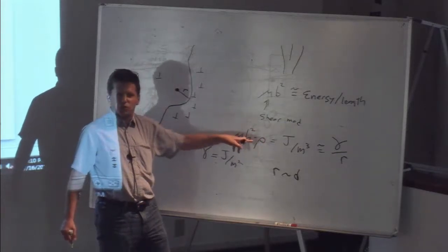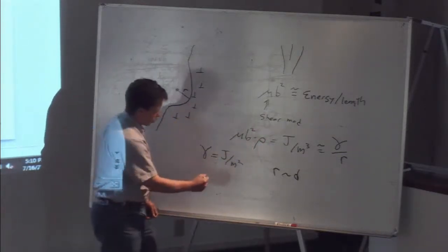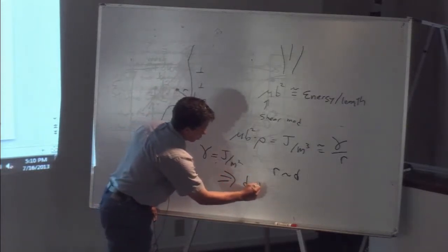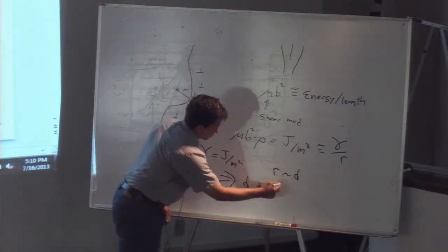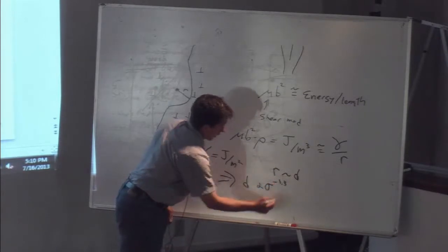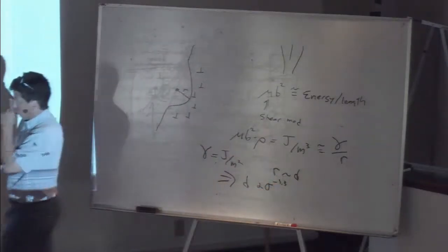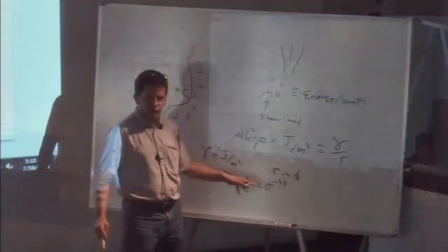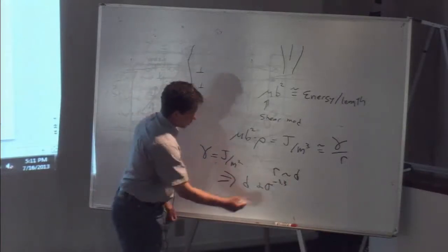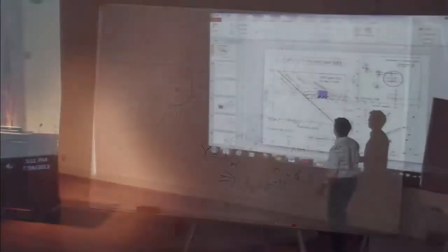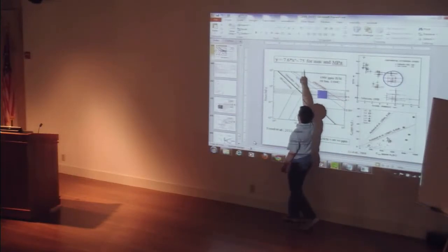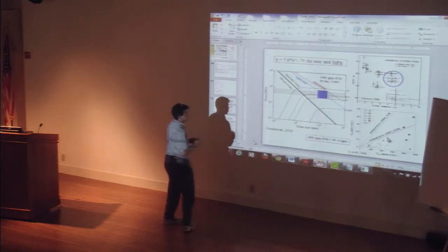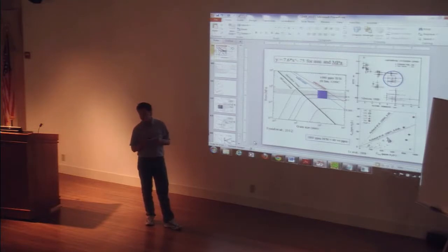And the dislocation density depends on stress. And you turn all of that into a relationship that gives you grain size is proportional to stress to the minus 1.3 power, roughly. Now, in these plots, we're going to turn it into stress versus grain size. So we just have to solve that equation with a proportionality constant. And that's what this is up here. So this is that equation, and that equation is for grain size in millimeters and stress in megapascals.